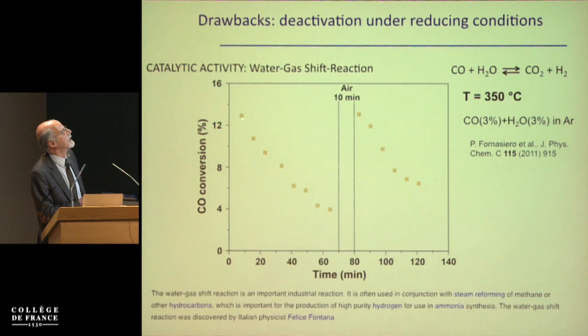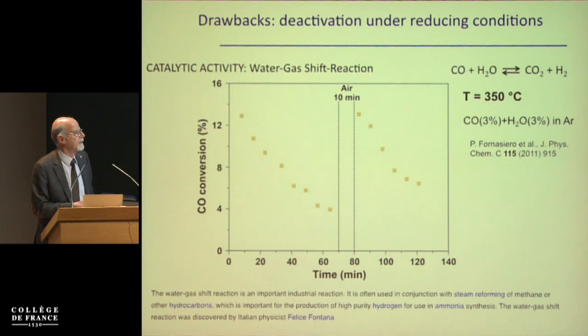And what they found is that the catalyst decreases in potency very visibly. To restart the catalytic activity, they had to expose it to air for 10 minutes, and then the activity was regained, but then again it decreased very quickly.